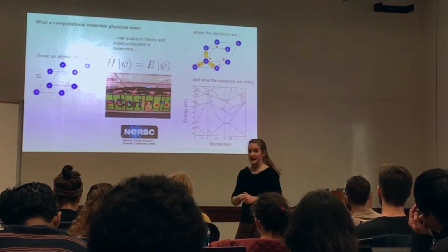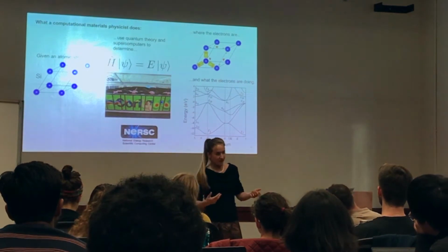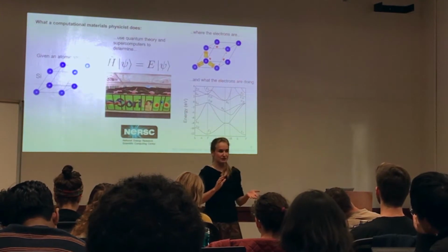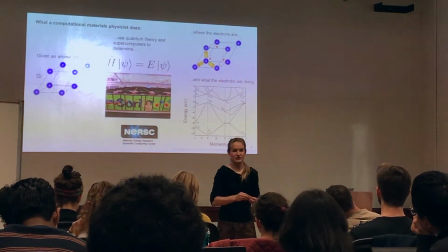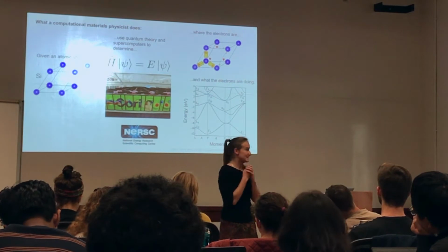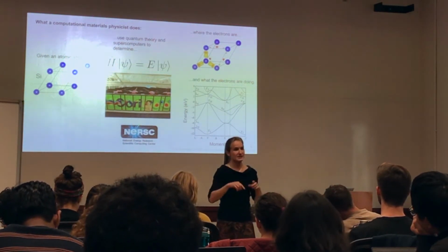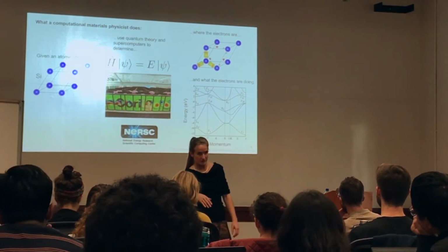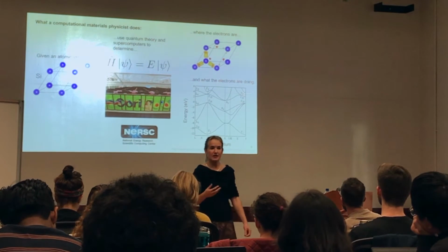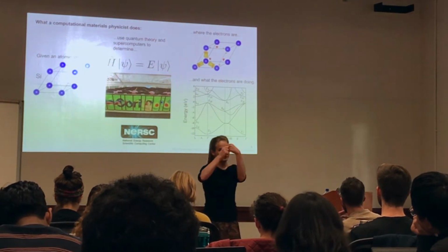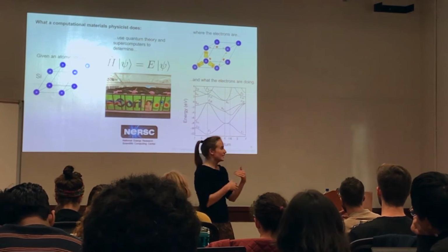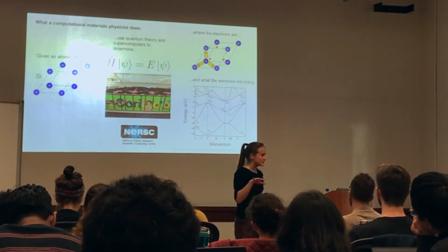And here I have what's called a band structure diagram, or more lovingly called a spaghetti plot by practitioners of the field. What this is showing is the relationship between energy and momentum of electrons in the silicon crystal. So basically, if you see really bendy bands, that means it's very easy for the electrons to move in the material. And if the bands are really flat, they're really not doing much. These types of diagrams help us assess how much energy it takes to go from one energy level to the next, and see what material properties this thing could have. It's a little bit like reading tea leaves, so there's a bit of a learning curve, but they're very useful.